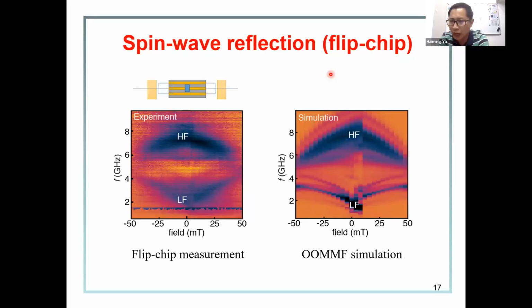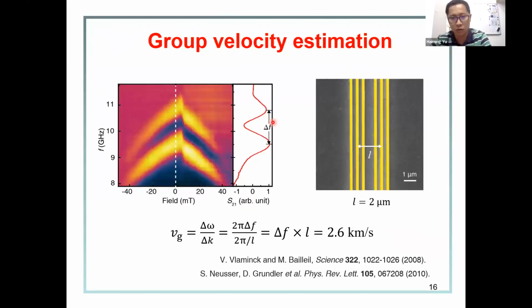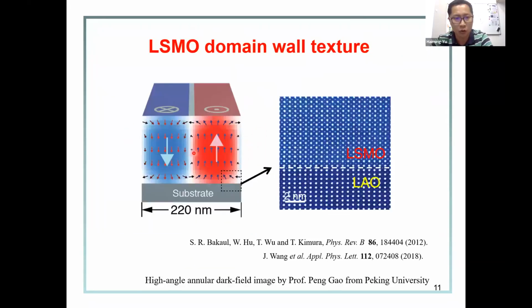At this point, my conjecture is that this is related to some kind of switching within the domain wall structure, because let me quickly go to the simulation of the domain wall. The domain wall structure has a core that is pointed either out of the screen or inside the screen. So with a small field sweeping in these directions, maybe the whole domain stripes appear the same, but the core may switch at a very small field. So this is our guess at this point.